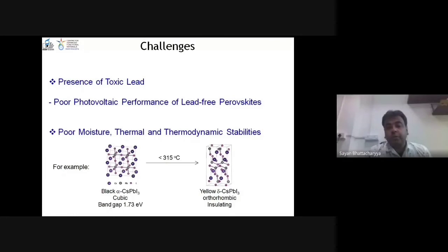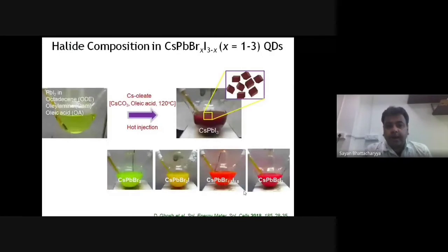It has a band gap of 1.73, but this orthorhombic phase has a large band gap, so it becomes insulating. This is one work which was done in our lab a few years back. We used surfactants because in nanoparticles, when you make small particles, the surface energy is always high, and every system tries to minimize the energy. So they start to join together and agglomerate. If you have a surfactant coating on the surface of these particles, you can avoid that and retain those small particles.